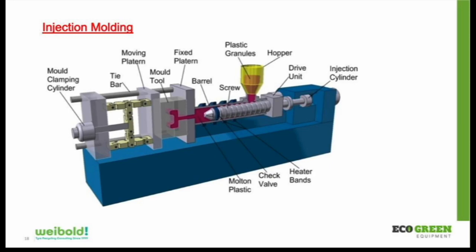Now you may have to, or this is a good thing, you may have to adjust your temperatures, but you would be adjusting them down. And a good example is we had a client that was manufacturing a specific part at about 365 degrees Fahrenheit with the all plastic material, and when they used our 50/50 rubber plastic blend, they were actually able to process at about 320, about 45 degrees less, which is significant.